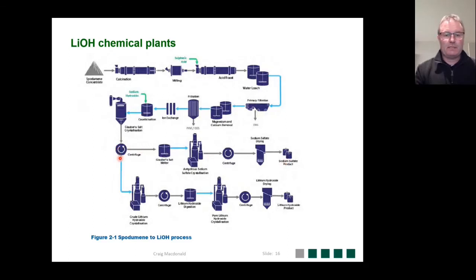What is more interesting perhaps is the lithium, which remains in the liquor from the centrifuge. It's then passed on to a crude lithium hydroxide crystallizer step. There may be more than one crude lithium hydroxide crystallizer. This is basically purification from this point onwards. The solids from the crude lithium crystallizer are then passed on to a centrifuge. The lithium hydroxide is redigested and then recrystallized in a pure lithium hydroxide crystallizer. The solids now are at an acceptable quality. It's then dewatered in a centrifuge, dried, bagged, and sold off as the final product of lithium hydroxide, and that product is then sold to battery manufacturers.